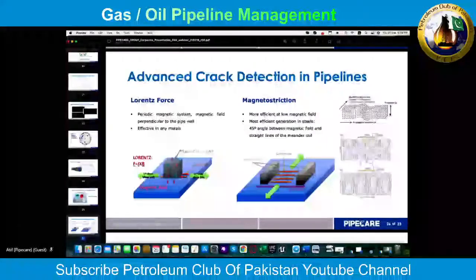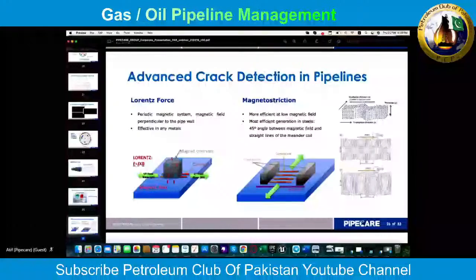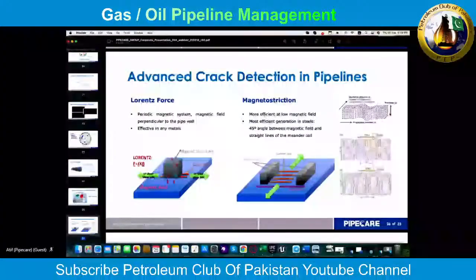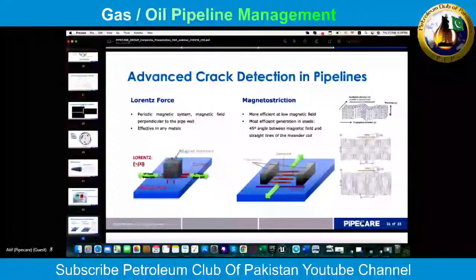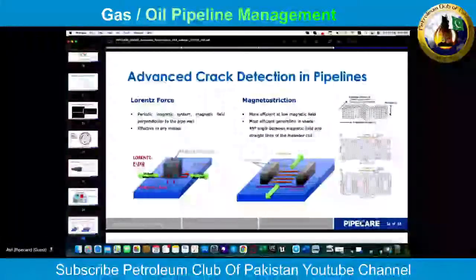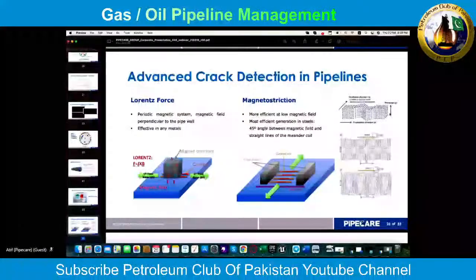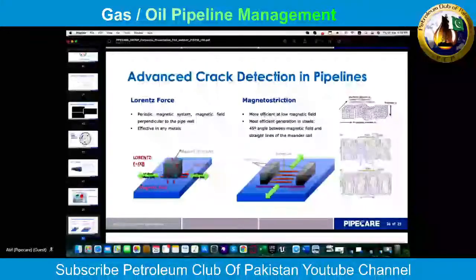So what's happening is that one of two methods can be used. One is using Lorentz force, one is using magnetostriction. The result of both methods is the same, that the metal grid is oscillating and creating an ultrasound or even different types of ultrasound inside the pipe wall. The difference between the Lorentz force and the magnetostriction is that magnetostriction has certain advantages, as it creates a static magnetic field and an oscillating electromagnetic field. This has benefits when it comes to better signal-to-noise ratio of the reflected signals.